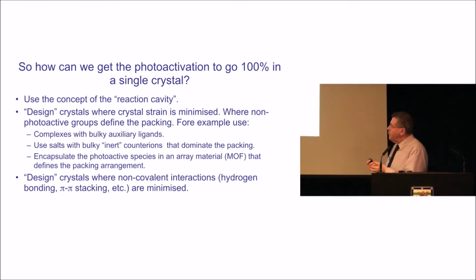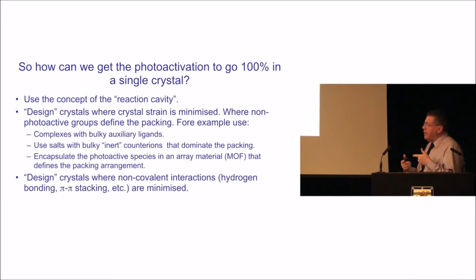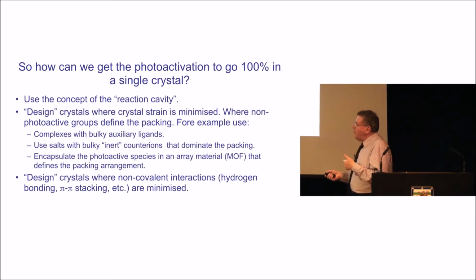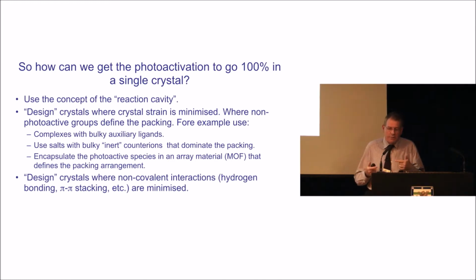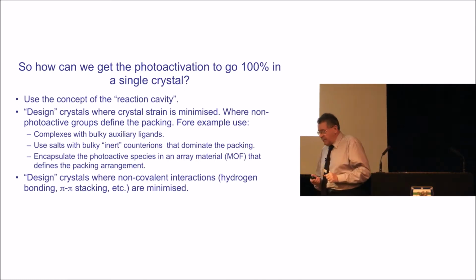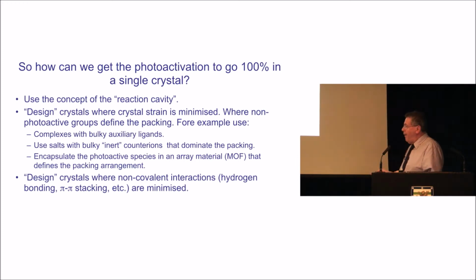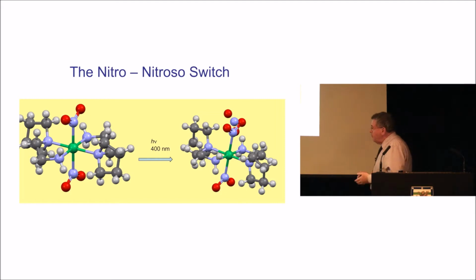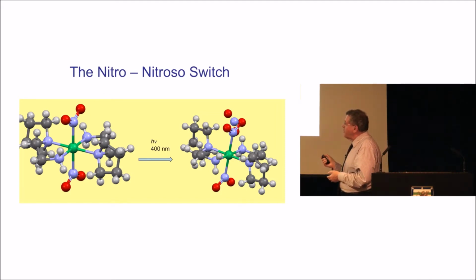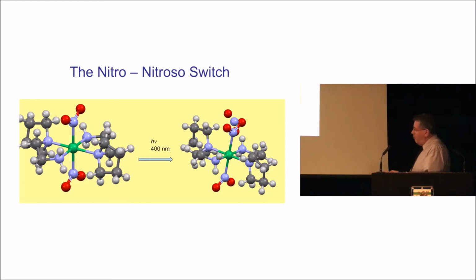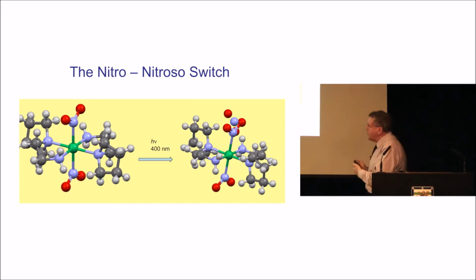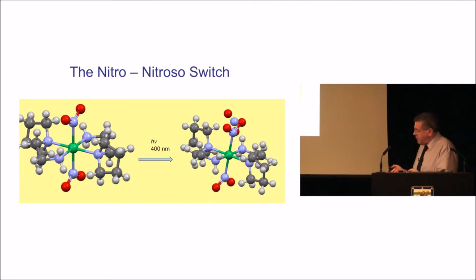And Neil Champness and Mike George have done some elegant work with metal organic frameworks allowing this to happen. So what we want to do is design crystals where there's this cavity, where there's a minimum amount of non-covalent interactions to allow this to go without having to go over a particularly high energy barrier. And we decided to look at the nitro to nitrito species, and here's an example of a partial conversion with 400 nanometer light. You can see the N-bound partially goes to O-bound. How do we get that up to 100%?